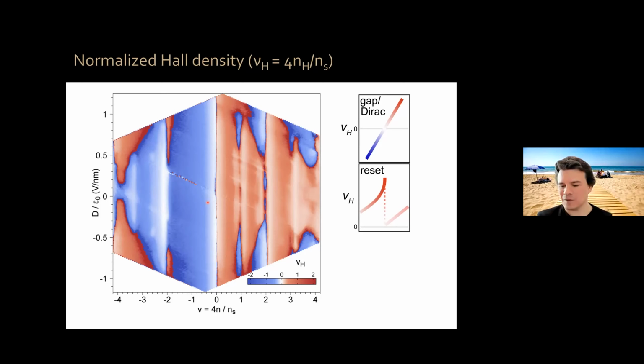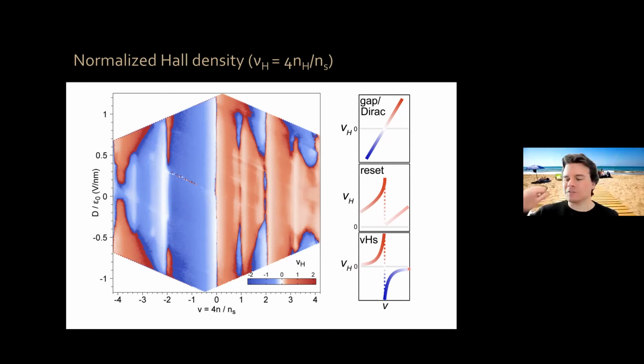And then the last feature corresponds to a van Hove singularity. The normalized Hall density grows and then abruptly flips sign, and then goes towards 0. At a van Hove singularity, your R_XY, your Hall voltage, goes smoothly through 0, which means 1 over your Hall voltage, so the Hall density, diverges. And that's something that you can see, for example, here. You go from light blue to darker blue, then it flips sign to dark red, and then goes to light red. So you see this type of behavior there, and that is seen in many other places.